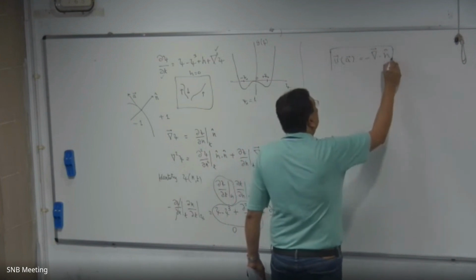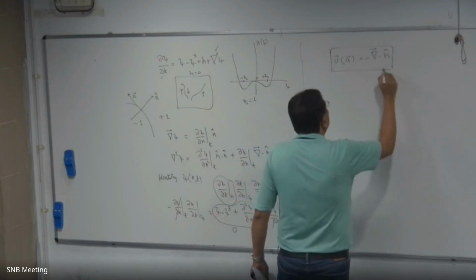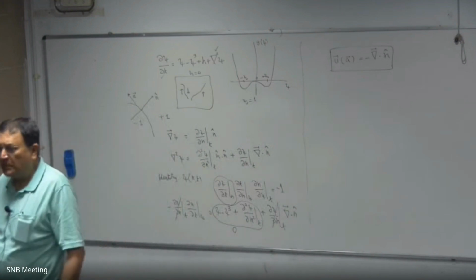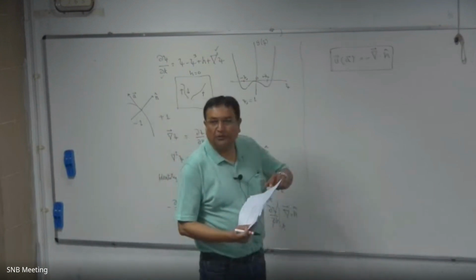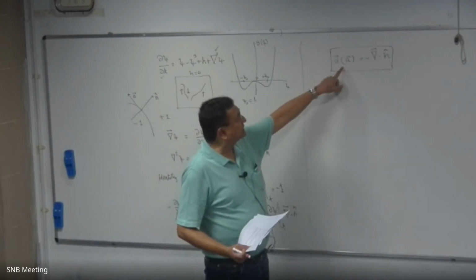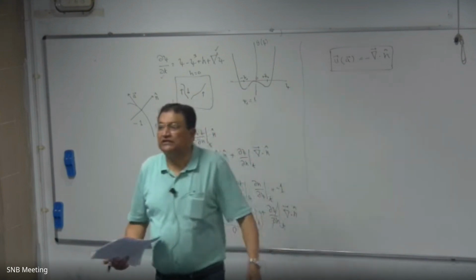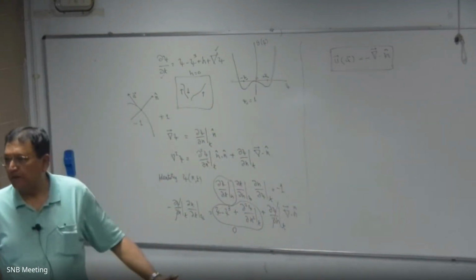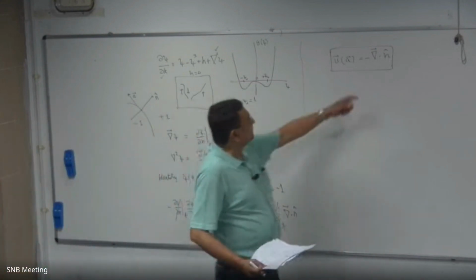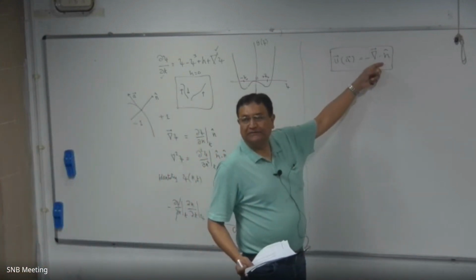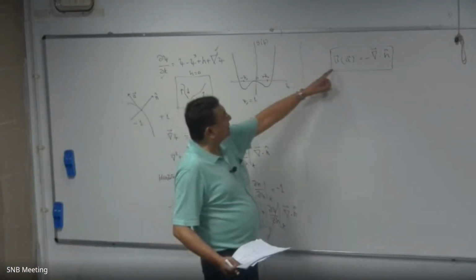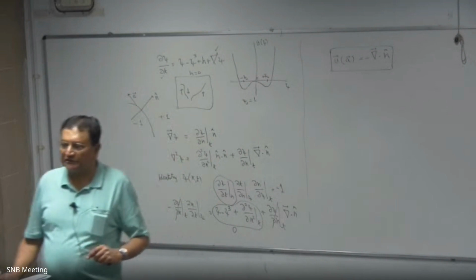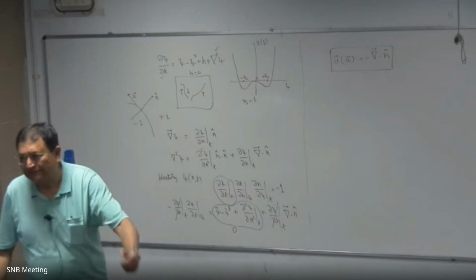This is a very important equation. I think it was first written down in the context of coarsening of soap foam. It applies in all sorts of different situations. Basically, what you're saying is the following: the velocity of the interface is just the local curvature of the interface. If you have a flat interface that does not vary with distance, the velocity is just identically 0, as we had discussed. But any curvy interface will move with a certain velocity. The more curvy the interface, the faster it will move.